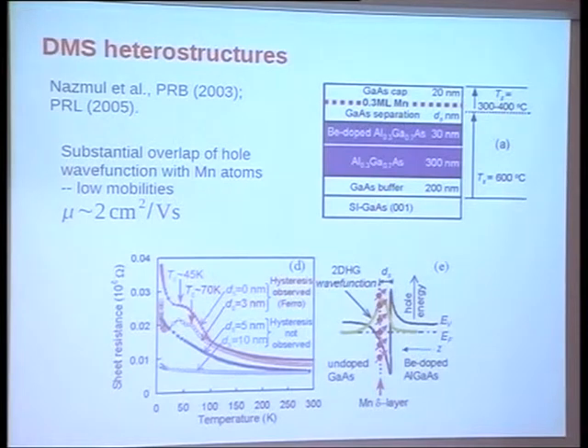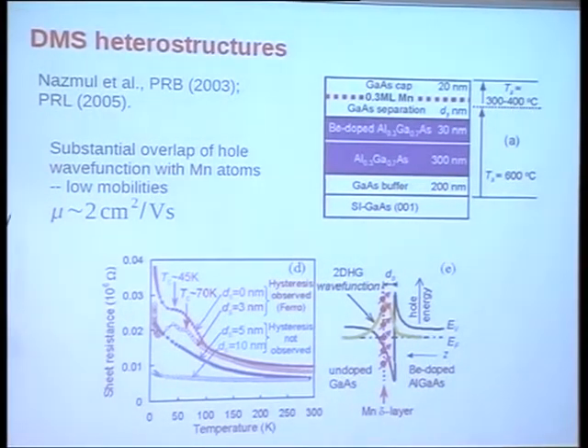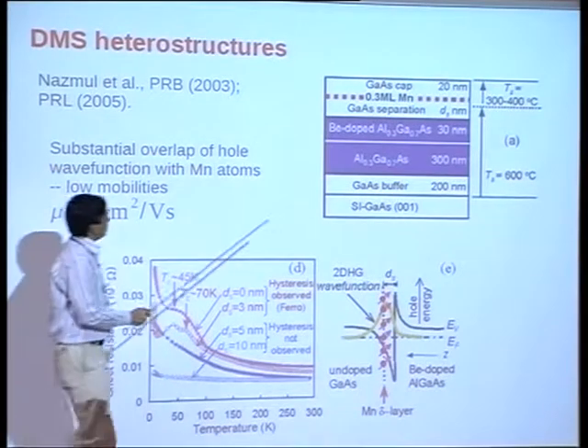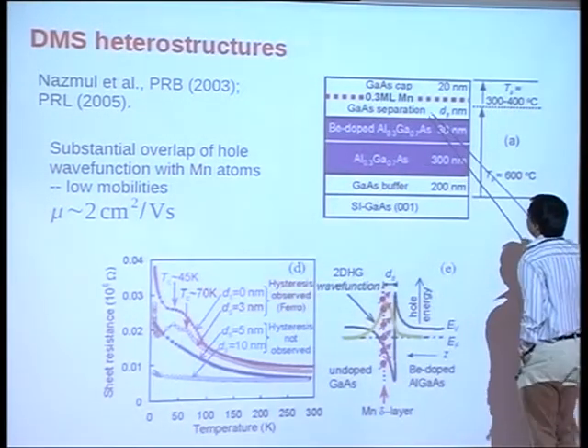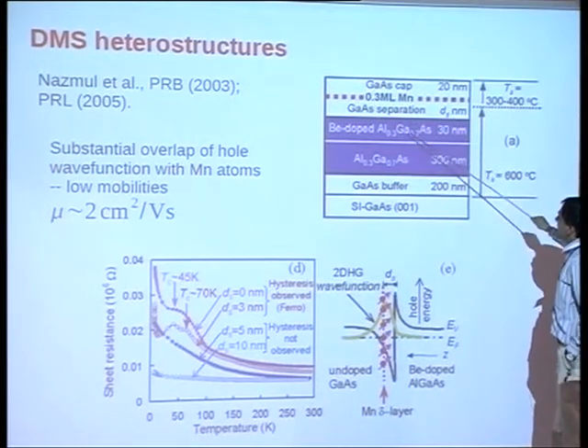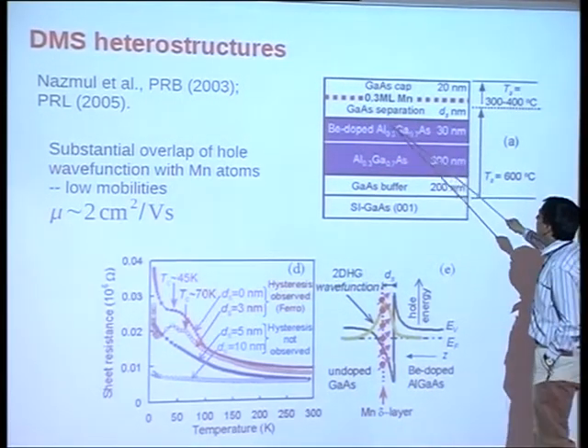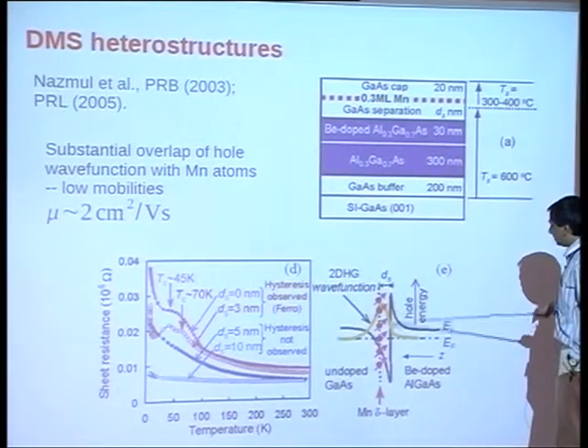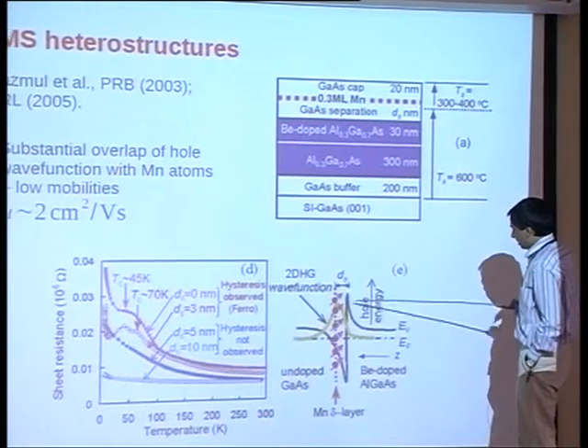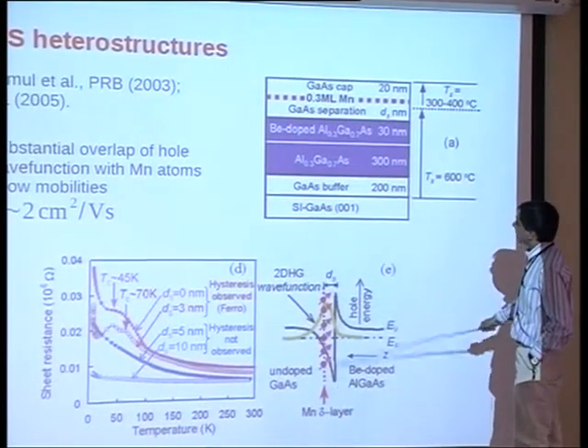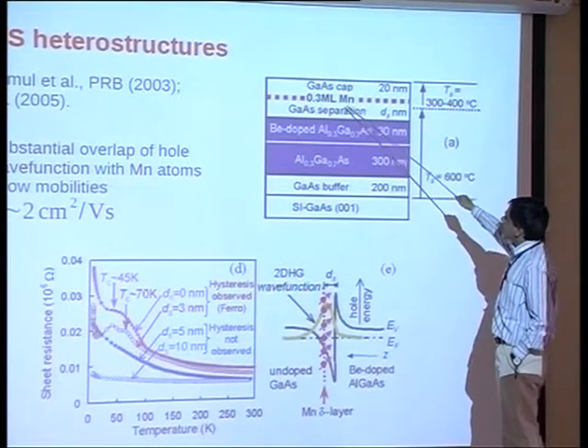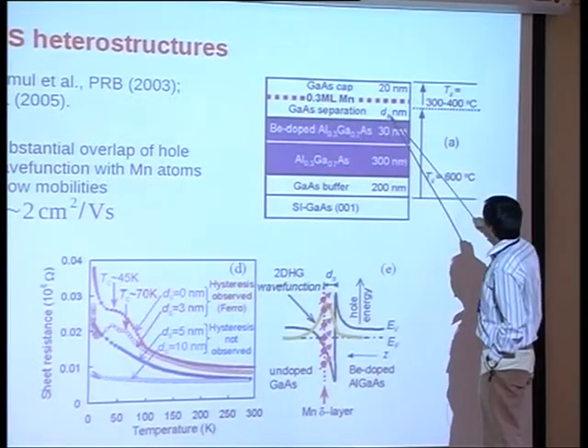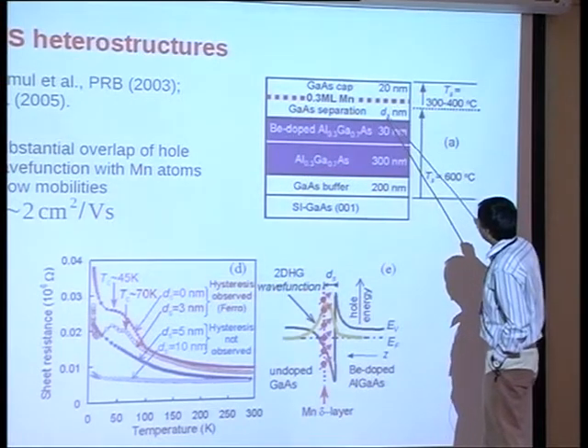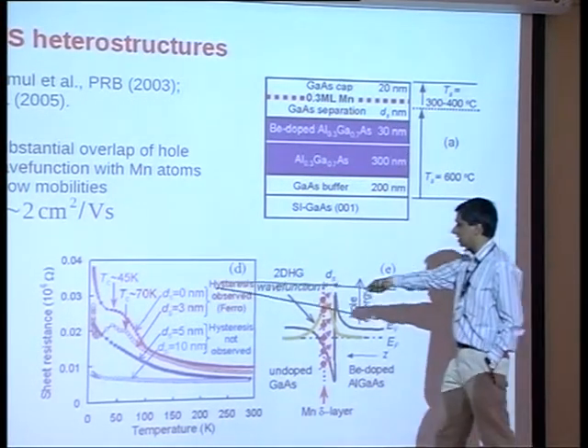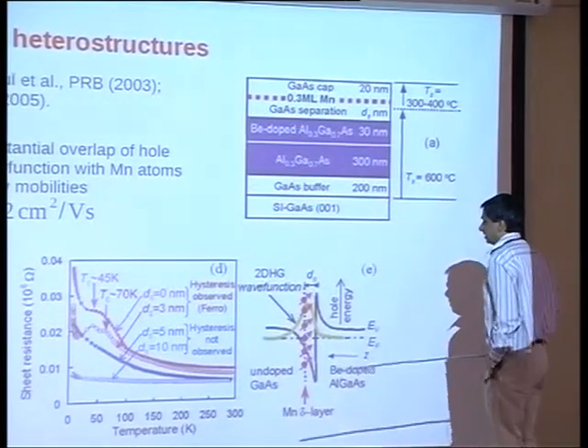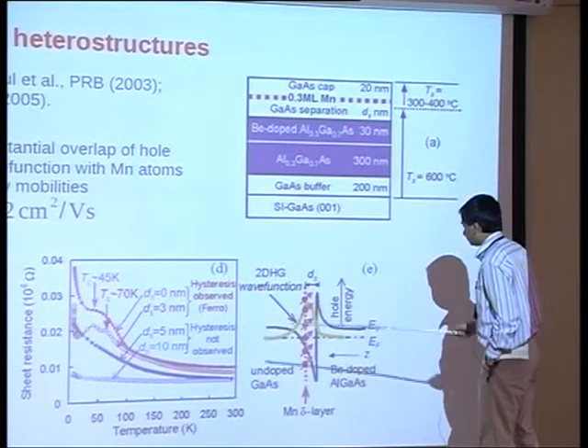Okay, so DMS heterostructures are relatively new, and here's the first one. Here what these people have done is, they have a gallium arsenide and a beryllium doped aluminium gallium arsenide here, and schematically the structure looks like this. The quantum well is formed on the side of manganese doping. The manganese is about 0.3 monolayers in density, and it's separated from the interface by some distance ds, and there are various values which the experimentalists have used in the fabrication.